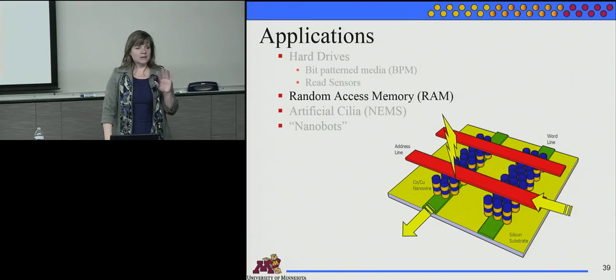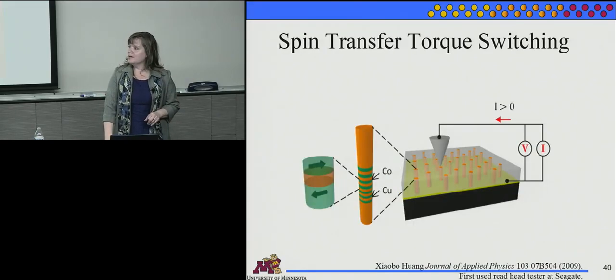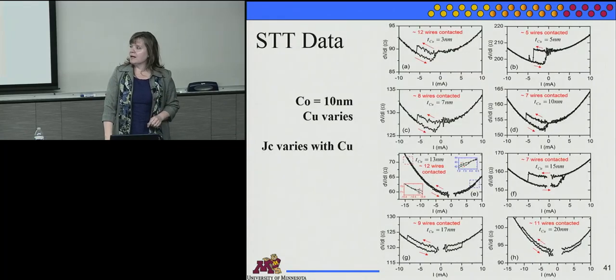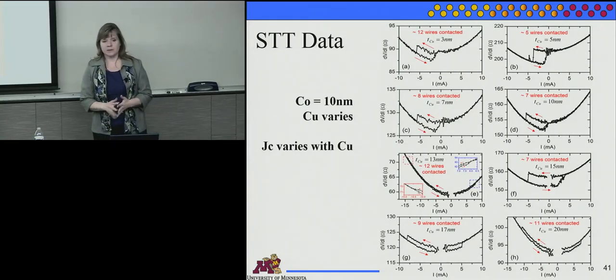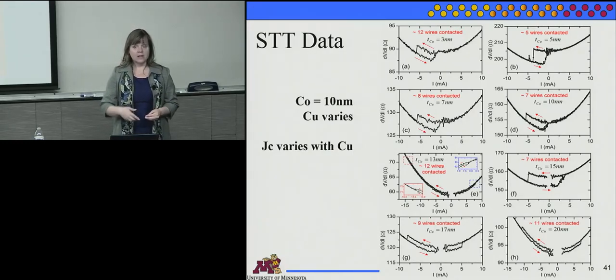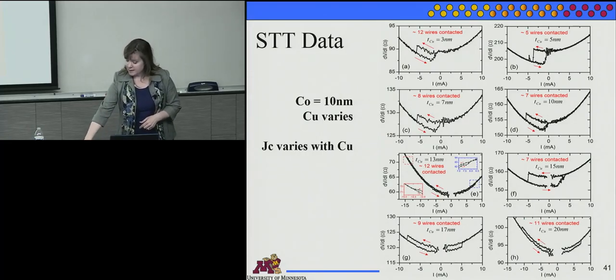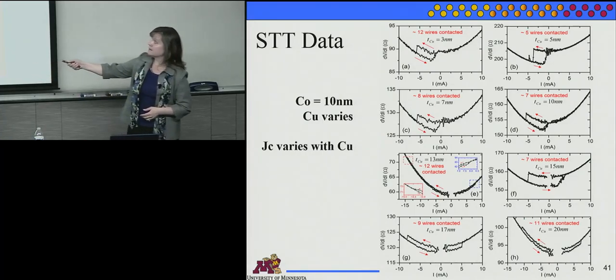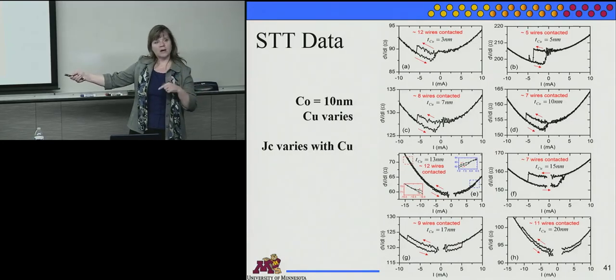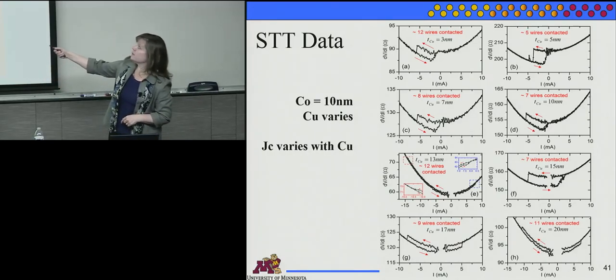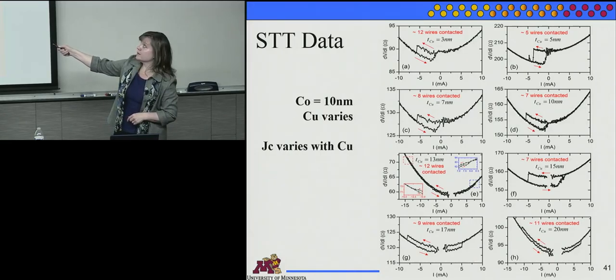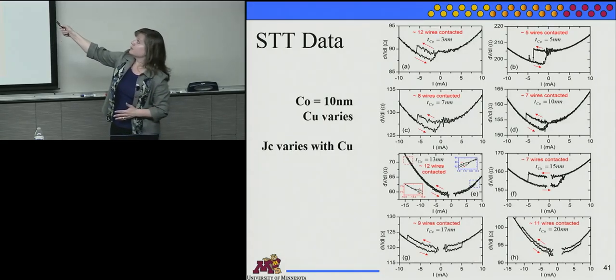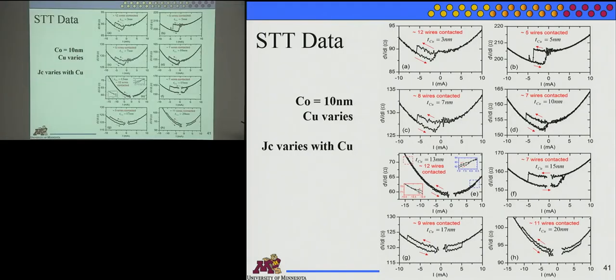All right, I told you I'd do something really quick in RAM and then hop to the bio. So the quick in RAM is how we measure it, and basically that we can get a lot of different switching currents and that they're fairly low. So for RAM, you want a low switching current density because you want to switch between ones and zeros. And a simple way to do that we found is just take 10 nanometer for all your cobalts, vary how much copper they're separated by. If you separate your cobalts by just a little bit of copper, you'll see a certain switching behavior. Put a little more copper and so on. When you get to about 13 and 15, now at least you see bipolar behavior, which is pretty important.